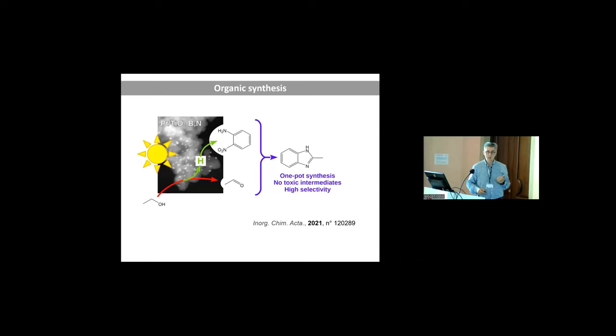For instance, you can use ethanol, let's call it bioethanol, let's say a water alcoholic solution. So you have water and ethanol. You have a photocatalyst like platinum supported on boron, nitrogen doped titanium nanoparticles, and you can do a one-step synthesis of benzimidazole by making from the alcohol hydrogen plus the aldehyde. The hydrogen can reduce nitro groups to amino groups, and then you can have the reaction of the aldehyde with the other products to make different important intermediates for pharmaceutical synthesis.